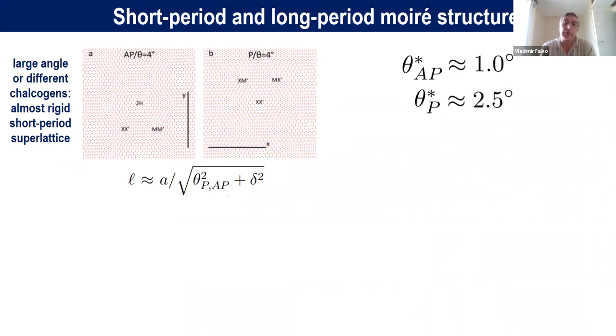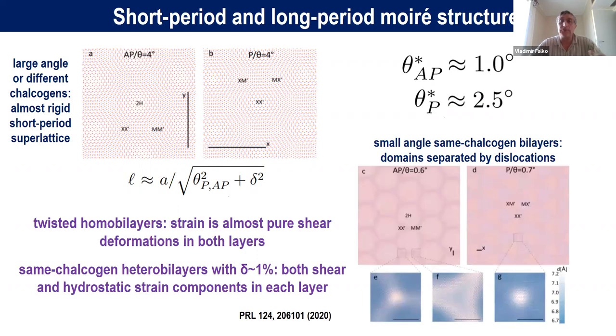And this is understandable based on the argument of comparing the area of domains that may form by reconstructing into energetically preferential stacking configurations and the energy cost of domain walls between those domains, which would scale linearly with the period of the superlattice. So if the angle is not small enough, or there is a lattice mismatch which is large enough, then the period of the superlattice is too short for the domains of preferential stacking to develop and take over the energy cost of the deformations required for their formation. And if the angles are smaller than those, then a distinct structure of domains appears. And this structure of domains is different for anti-parallel and for parallel orientation of unit cells.